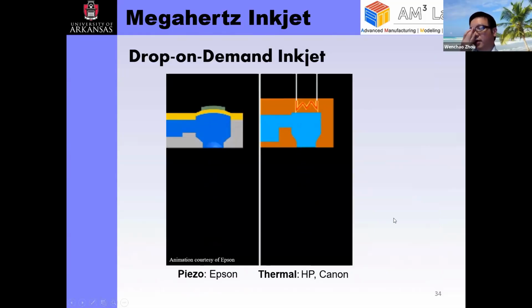So in the industry, there's two commonly used inkjet techniques. One is thermal inkjet printing, which uses a micro heater that heats up to 300 C to vaporize the ink into bubbles, and these bubbles force liquid out to form a droplet. These printheads are typically very low cost, and most commonly used in HP and Canon inkjet printers. It's sensitive to ink chemistry, and the cost is lower.